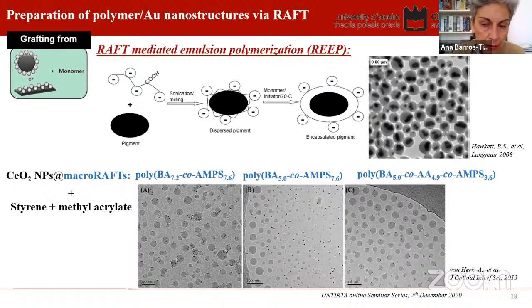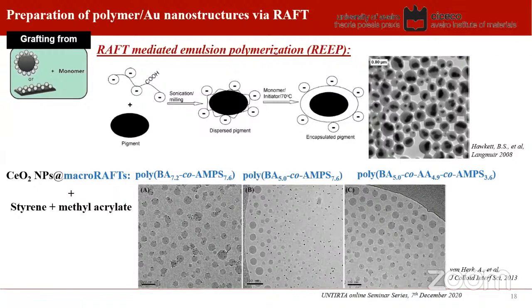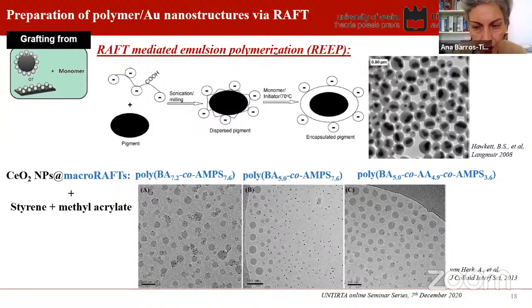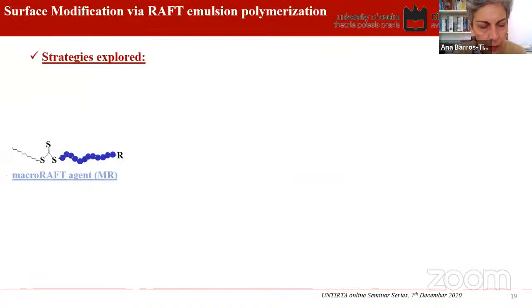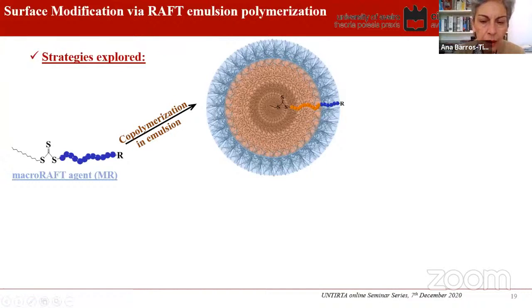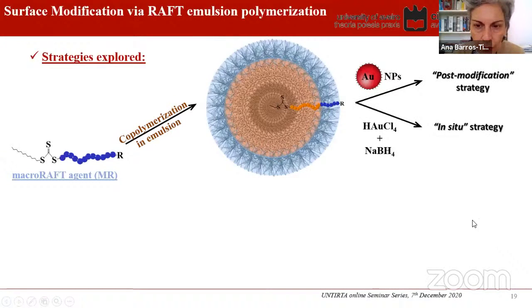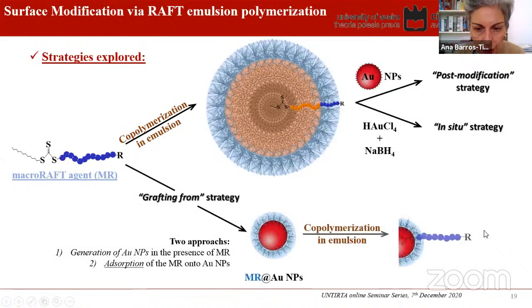So we looked further, and in the meantime, other works had been also reported using this combination of RAFT polymerization with emulsion polymerization. Of course, this requires very fine tuning of the size of the blocks of polymers that we use. So it's not as straightforward as it may sound, but the heart of the matter is it allows this neat encapsulation of nanoparticles. So with this, we decided to then consider a full evaluation of how to go about what we wanted.